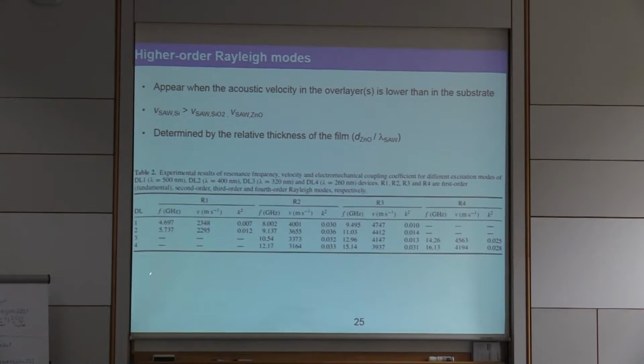What we see is that for the different delay lines, so 1 to 4, this corresponds to from 500 nanometer to 260 nanometer, we measure different modes. Sometimes we even don't measure the fundamental mode at all, because the electromechanical coupling is very small for this fundamental mode. But for the smaller device, smaller wavelength, we can measure up to the highest Rayleigh modes, where the difference is really coming from the different velocities for these different modes. So the different velocities for the given geometrically determined wavelength give us then the different resonance frequency, up to 16 gigahertz in this case for the fourth order Rayleigh mode in this multi-layer system.